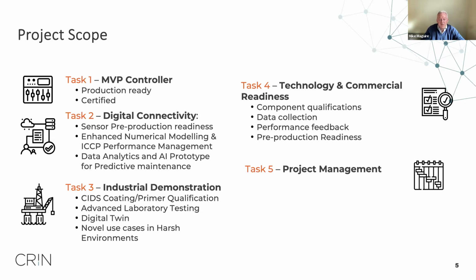As of now, we have a digital twin, or a numeric model, that's calibrated to be able to detect and locate very accurately damage on a piece of pipework. And in the previous demonstration, we were able to show that we could detect a scribe through the paint that was about 1.25 centimeters long by a millimeter wide. We contained that within about a 3 centimeter long band around the paint. So we believe that's a degree of accuracy beyond anything that industry might require.